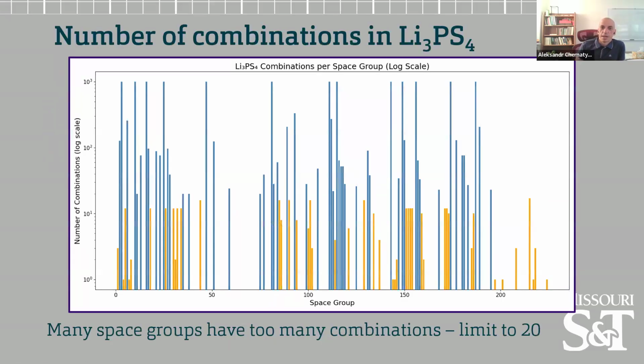This plot represents the number of possible combinations of arrangements of the atoms and rigid blocks among different Wyckoff positions in a given space group. Again, this plot was generated effectively automatically. Notice the log scale on the y-axis. The ones that are terminating at 1,000 are basically where we lost patience and said we're no longer going to count. There are so many different combinations that we're not really going to run this anyway, because it would imply that I need to run basically 1,000 different simulation units with different combinations.